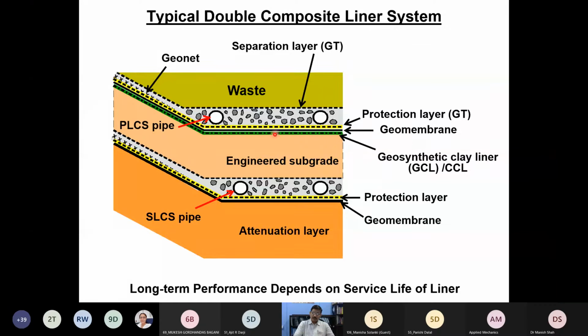Followed by the composite liner system, basically a primary geomembrane plus GCL. The primary objective of these two layers is to act as a perfect advective-diffusive barrier. If it's an intact geomembrane, we all know that for all polar compounds, the geomembrane is not going to leak even a single molecule of a polar compound. However, since geomembranes are made up of polymers, they diffuse the organic contaminants through their surfaces, even though they are intact. In such a case, the combination of the geomembrane and the GCL, or the geomembrane and compacted clay liner, behaves like a perfect diffusive barrier so that the contaminant impact on the surrounding geo-environment is limited or controlled. We cannot say that it's completely ignored.